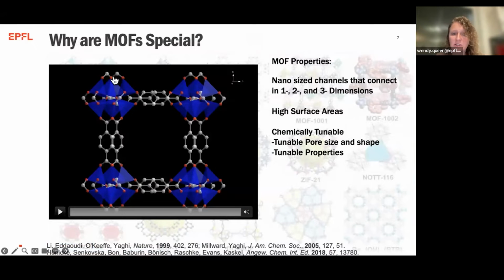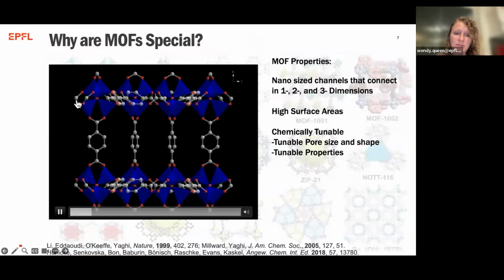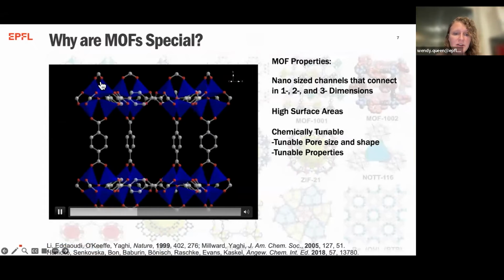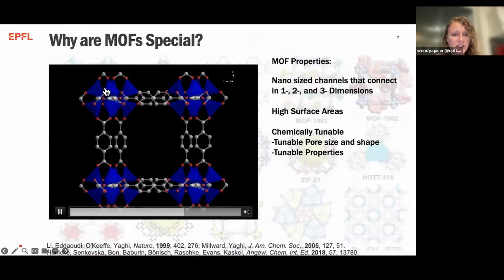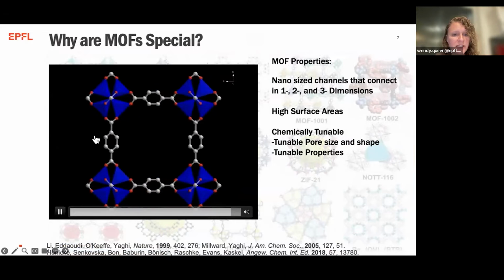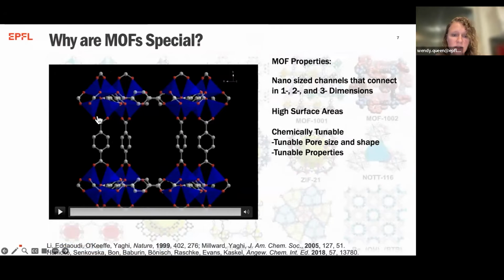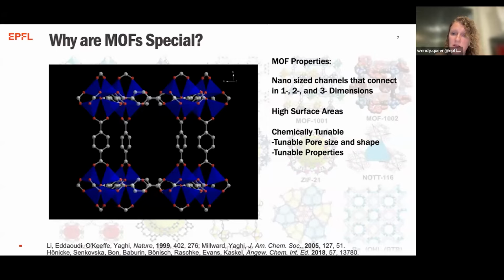So if we take a look at a real MOF, this is the prototypical MOF referred to as MOF5. Here you can see these metal ion clusters with zinc ions in blue interlinked by these rigid organic linear units shown here. Now, these materials are really interesting because you can easily change the building blocks that you have, the metals or the ligands. And as a result, tens of thousands of these materials have been synthesized to date. So we can engineer materials with various pore sizes, with channels that propagate in 1, 2, and 3 dimensions.